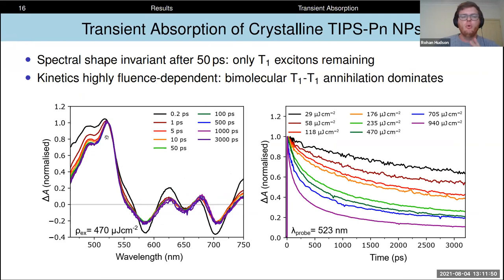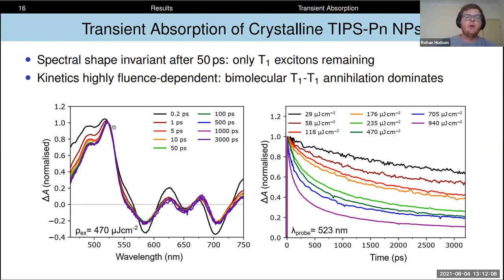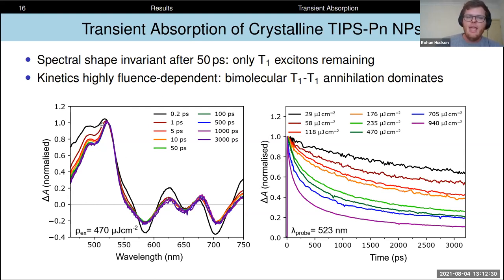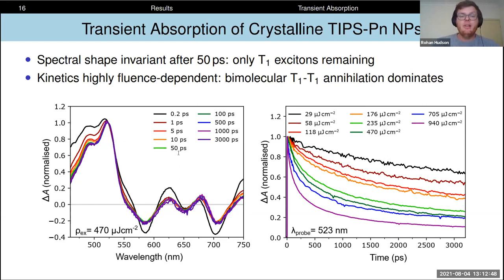On the left I've shown transient absorption spectra of our nanoparticles at a range of different delay times, normalised to this large positive feature at about 520 nanometers. You can see that the shape of these spectra changes quite dramatically over the first 10 to 20 picoseconds — this evolution actually corresponds to the singlet fission process taking place, where singlet excitons are converting into triplet excitons. We know from previous work that this large positive feature centred at 523 nanometers is an excited state absorption from triplet excitons in TIPS pentacene. Beyond about 50 picoseconds in delay, there's no further shape change in these spectra, indicating no further evolution of the system beyond the triplet excitons decaying.